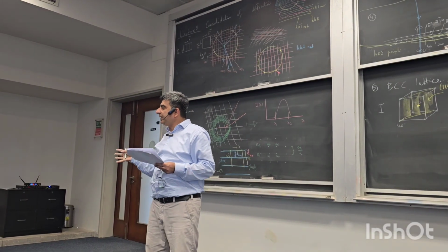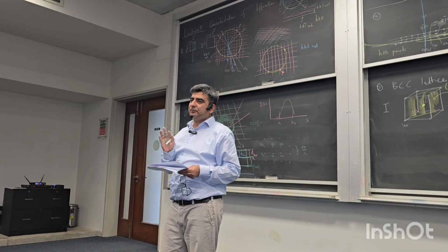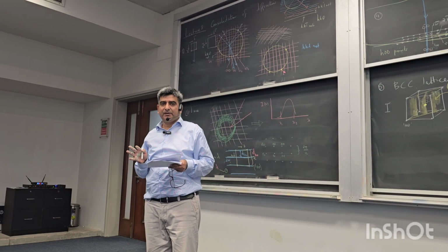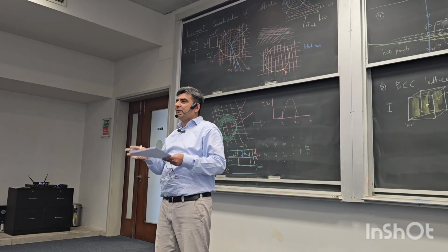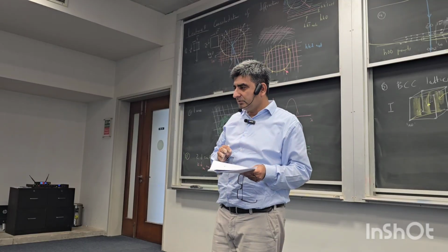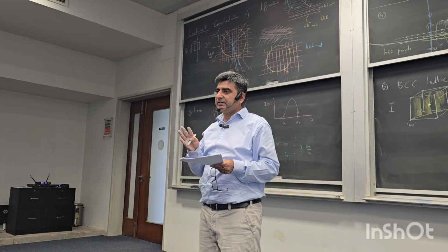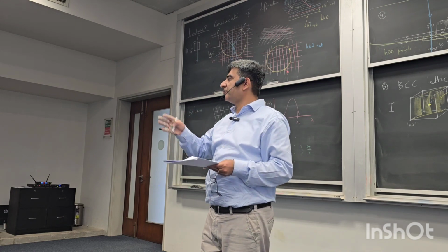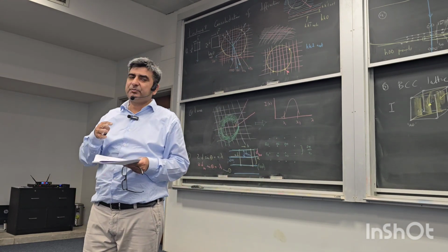So if you look at the peaks that are coming out from a diffraction experiment, first of all the experiment will give you thetas. From those thetas you have to infer the HKL values. This is called identifying or indexing the peaks. You have to index the peaks. You have to tell which peak corresponds to which plane, to which reciprocal lattice point. And I'll show you an example for this probably in the next class.